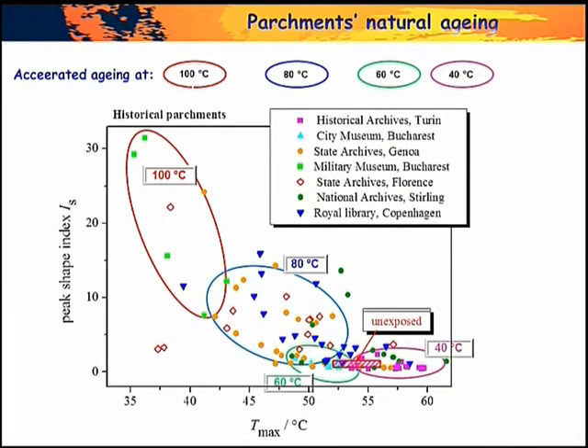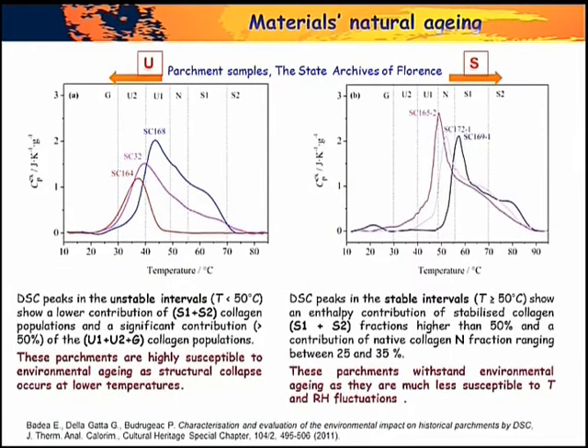Then, plotting the historical parchment, a surprising observation came out, that historical parchments also tend to group depending on their provenance, that means on their conservation history. For example, bindings from the historical archives of Turin are more or less grouped in the same area where parchment aged at 40 degrees Celsius group. So this is a very nice information.